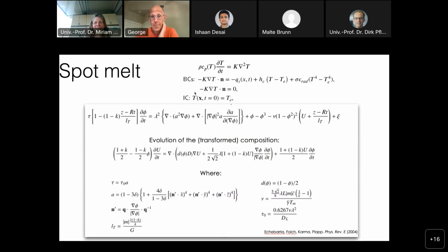So these are the simplified set of PDEs. This is a heat transfer problem. The heat capacity and in fact the conductivity depend nonlinearly on the temperature. Here we ignore this dependence. The boundary condition on the top surface, where the laser is, will be the laser source, some convective term and some radiative term. And then on the other parts of the boundary, we have zero flux, or assume it's large enough. And then given the temperature profile, we solve this phi here, which will essentially capture